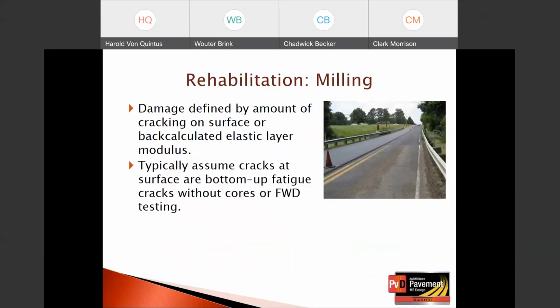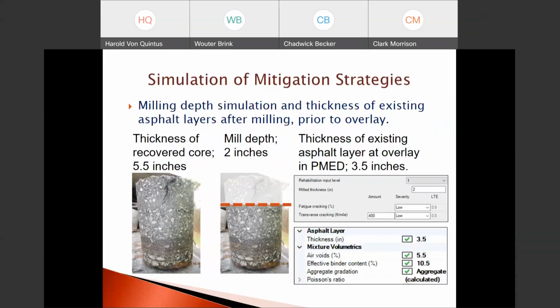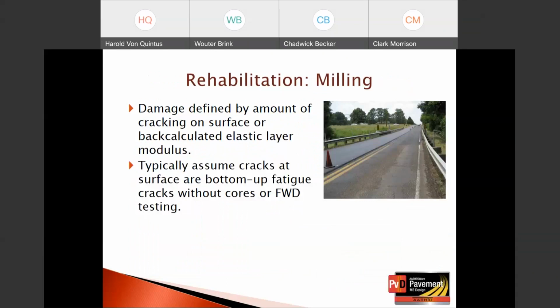Okay, so the damage, let me go back. If we're doing a mill and overlay, and we're doing rehab input level 2, how do we decide on the amount of fatigue cracks that are remaining in the existing pavement? So damage is typically defined by the amount of cracking on the surface or back calculated using elastic layer theory for rehab input level 1. Those cracks are assumed at the surface or bottom-up fatigue cracks if we do not have cores or FWD testing.